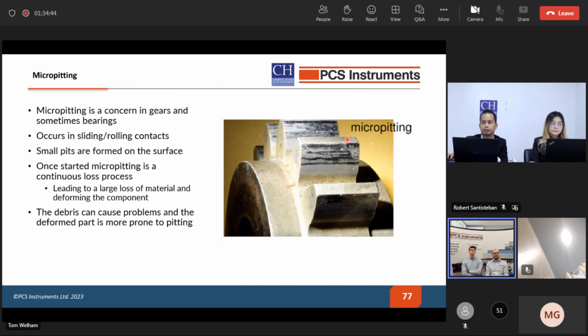And once micropitting has started, it'll spread across the whole surface, creating these dense crack networks, leading to a large, continuous loss of material. And this can be akin to something like wear, but micropitting is a fatigue-driven process, unlike wear. And the debris can cause problems as well, as it can get inside the contact and actually accelerate the damage as the micropitting is formed.